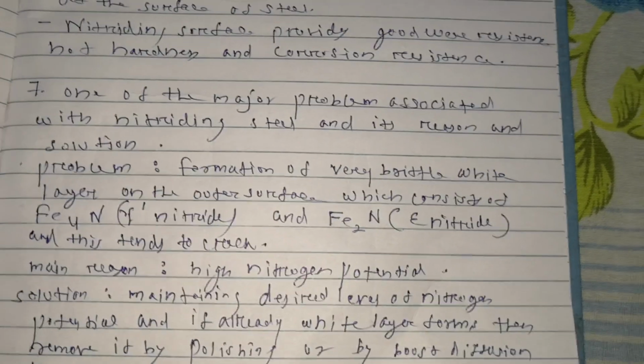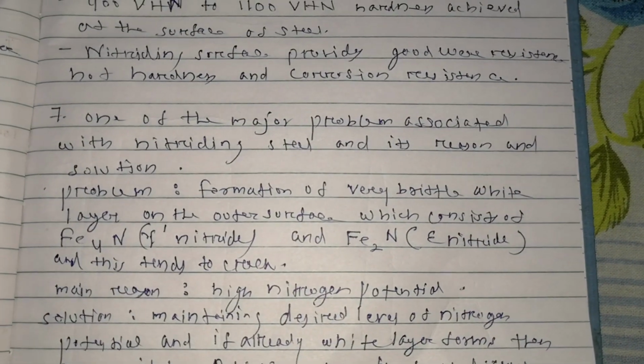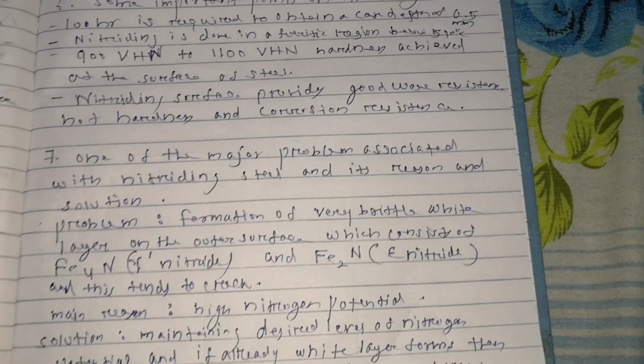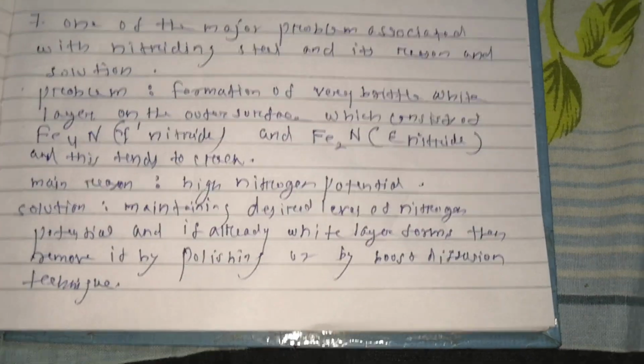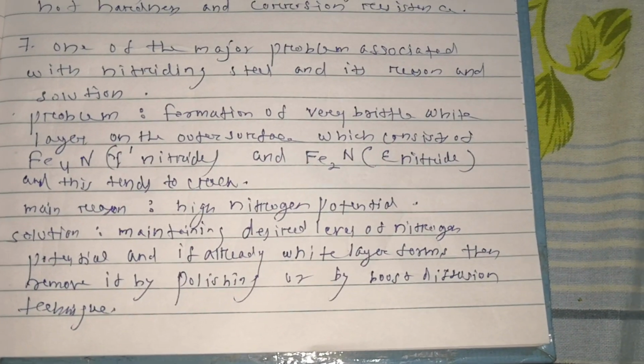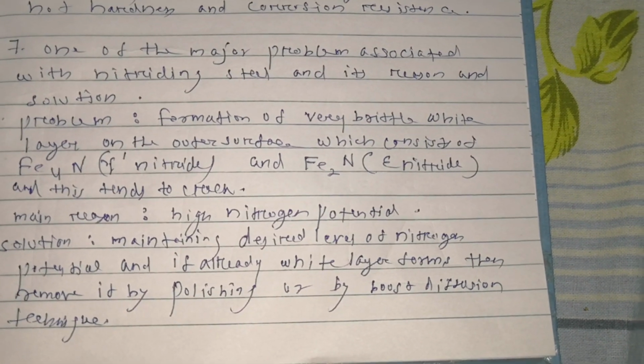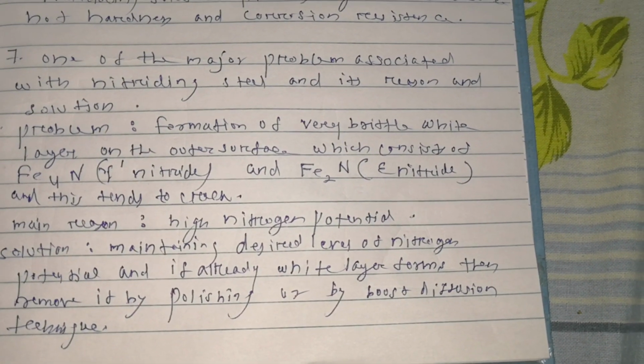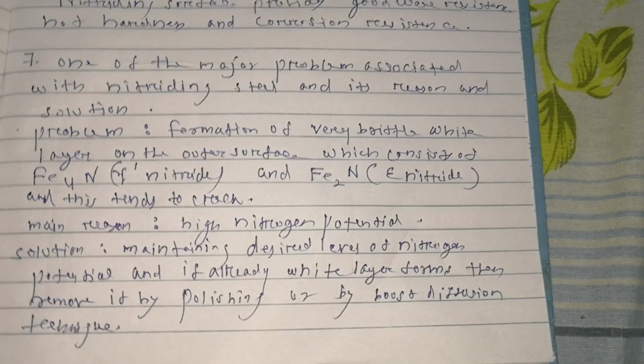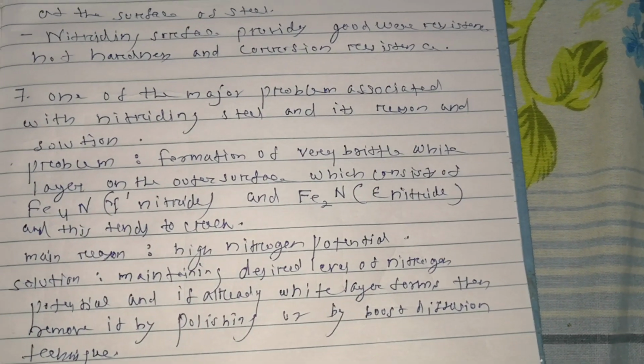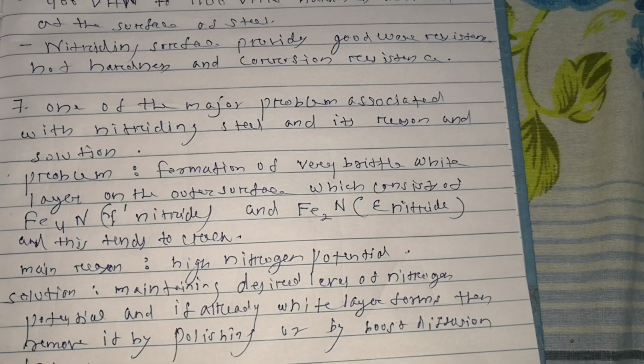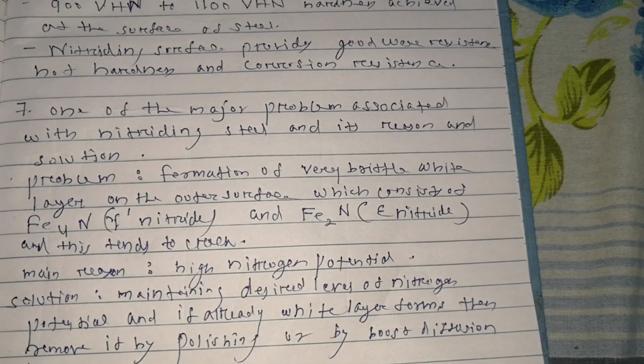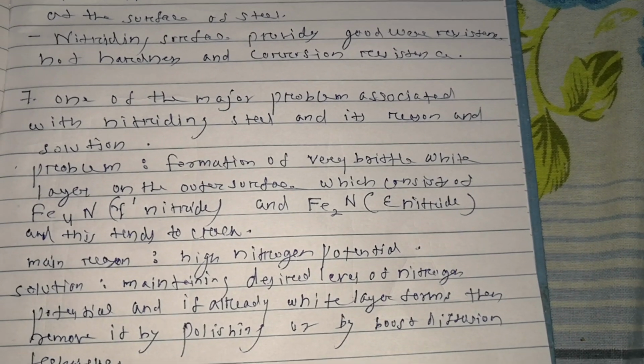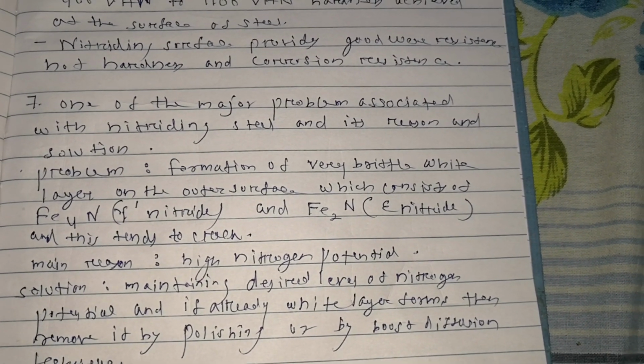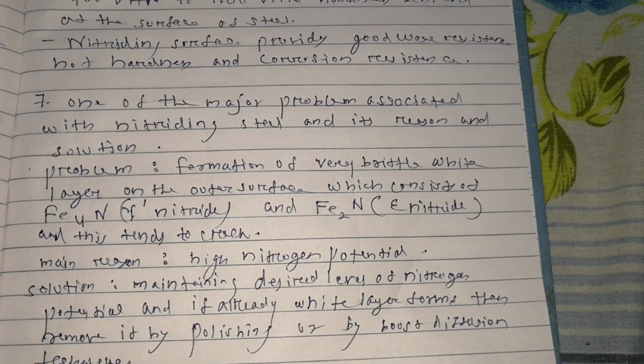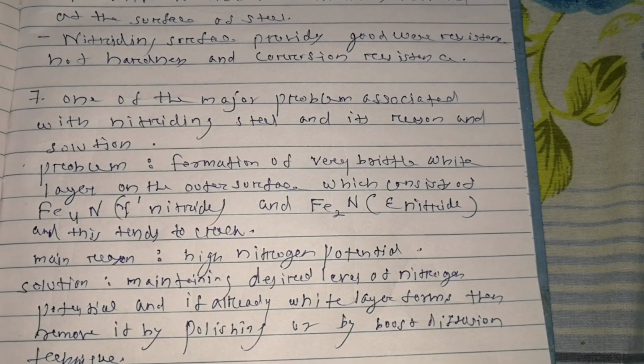Then we'll discuss one of the major problems associated with nitriding of steel and its reason and its solution. The problem associated with the nitriding operation is formation of a very brittle white layer on the outer surface of the steel. This brittle layer is basically composed of Fe4N, which is gamma prime nitride, and Fe2N, which is epsilon nitride. And due to formation of these nitrides, the surface becomes brittle and it tends to crack.